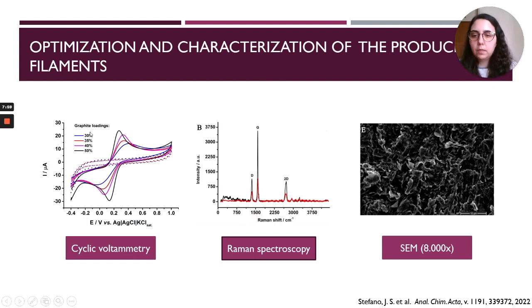So 50% was already very brittle. Then the optimized condition was 40%. We still have a good current and a good peak separation. So this filament was chosen as the ideal one, and this will be the one used for further experiments. So 40% in graphite loading.